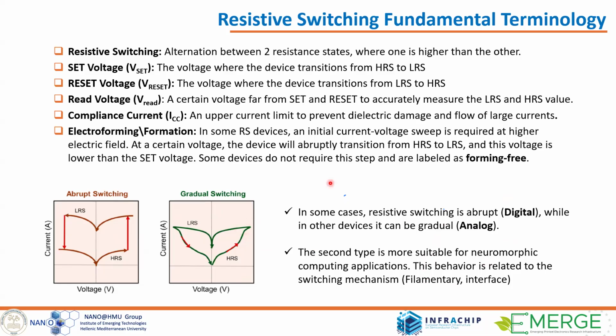For the terminology, we have the set voltage and reset voltage. Then we have the read voltage, where we read the state of the device. For example, usually it's a very low 50 millivolts, something like that. So we apply a positive voltage and then we read the resistance at 50 millivolts. We will read a high current, so a low resistance state. If we apply minus, let's say, 1, 2 volts, and we read here, then we are going to read the high resistance state.